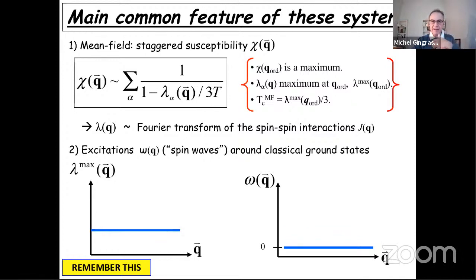And in parallel, if you identify a candidate ground state for such a system and you do a spin wave expansion about the ground state, for example, you find that there are a finite number of flat bands over the whole Brillouin zone. So the system is extremely soft. And this softness of this extensive number of ground states is what drives the system to be extremely fragile and a good platform to look for exotic physics, including large quantum fluctuations.